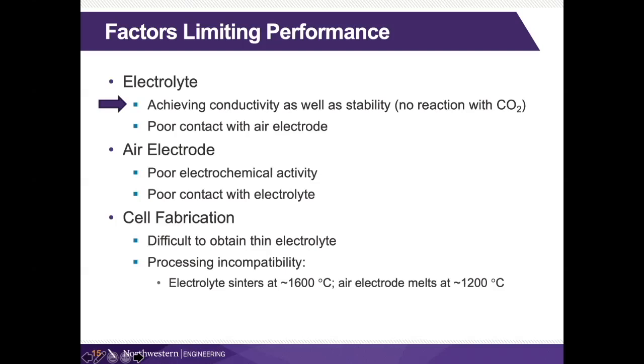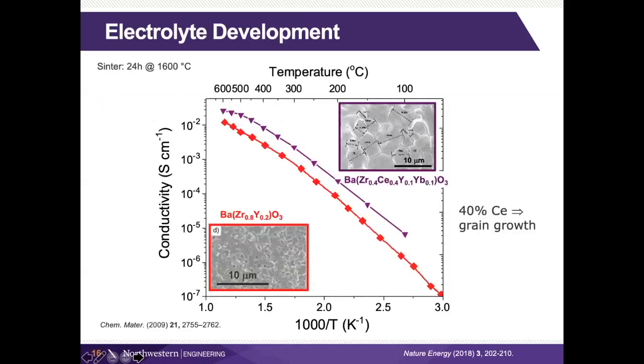And so we set about to tackle this, first of all, for just making some better electrolytes. And the way that we did that had to do with modifying the chemistry just a little bit. And when you modify the chemistry, what happens is that you're able to get some very large grain materials. So this is our polycrystalline electrolyte. And it's the grain boundaries that are very resistive in these materials. So if you have a large grain material, the number of these barriers that you have to cross is diminished compared to this fine grain material. This is very refractory and very difficult to work with. And again, these small grains means that you have lots of these barriers to go across.